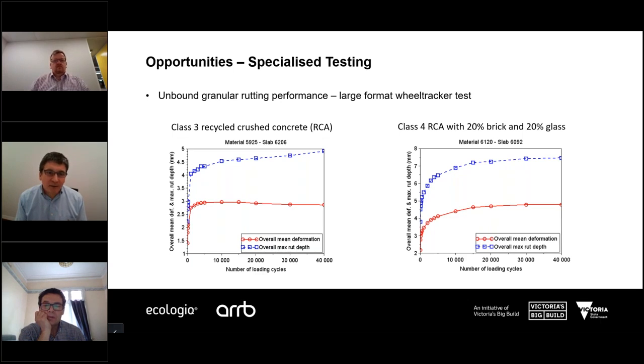So on the left, we have a class 3 subbase recycled crushed concrete as an unbound material. And you can see that the rutting in this test is about, on the bottom line there, about 3 millimeters at the end of 40,000 cycles, but its performance is quite consistent. Initial development of deformation, and then it sort of plateaus out.